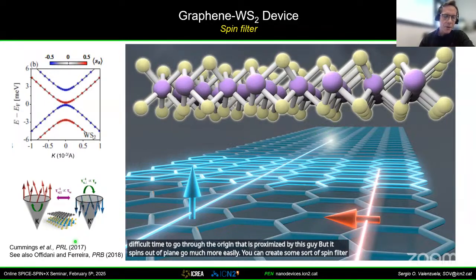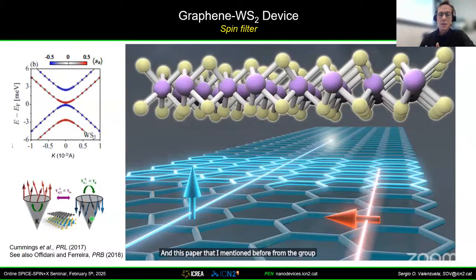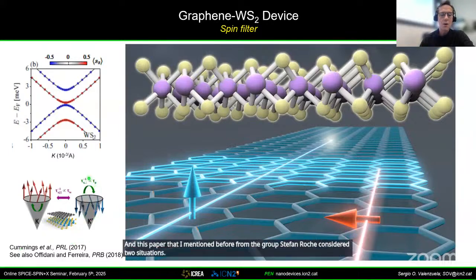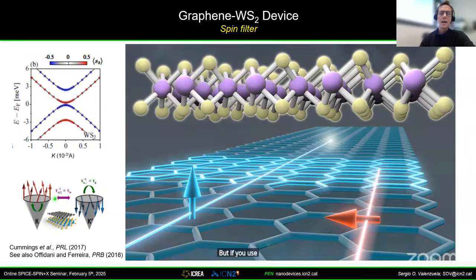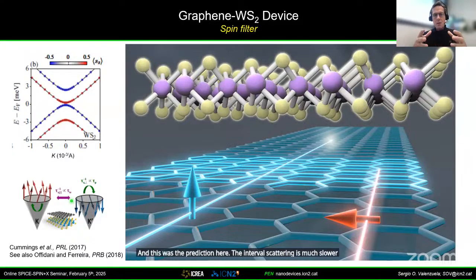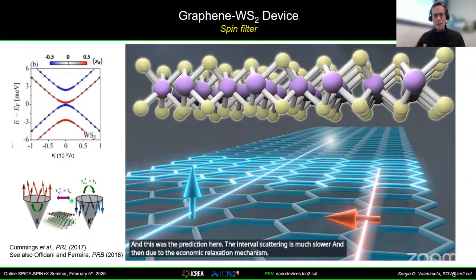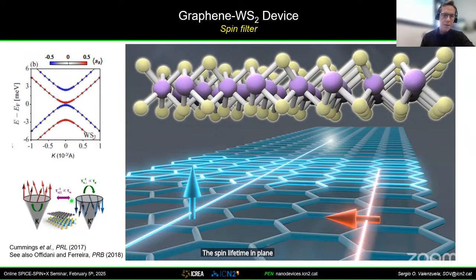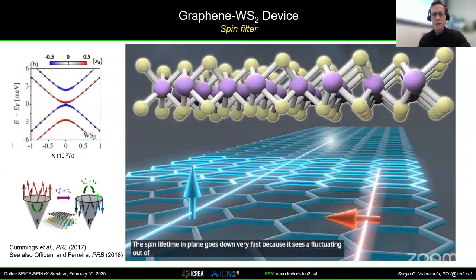And this paper that I mentioned before from the group of Stefan Roche considered 2 situations, one in which you have only intra-valley scattering, momentum scattering. In this case, the spin lifetime out of plane is shorter than in plane. It's only relaxed by the spin-orbit interaction. But if you induce inter-valley scattering, then the anisotropy is like what we observed. And this was the prediction here. The inter-valley scattering is much slower. And then due to the Dyakonov-Perel relaxation mechanism, the spin lifetime in plane goes down very fast because it sees a fluctuating out of plane magnetic field at each scattering event.